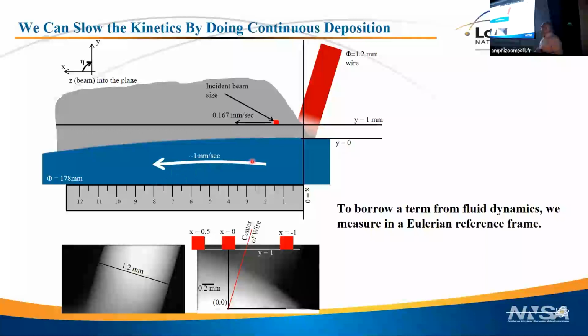So here's the wheel, and here's the wire schematically, and here's the deposit. As the wheel rotates this way, solid material is deposited onto this surface. We did do some imaging. This is what the wire looks like in image. And here's the deposit. You can see this misty area here. That's because, again, our image took 1/10 of a second to collect. So we're imaging over several droplets going across this. So the droplets just look like mist.